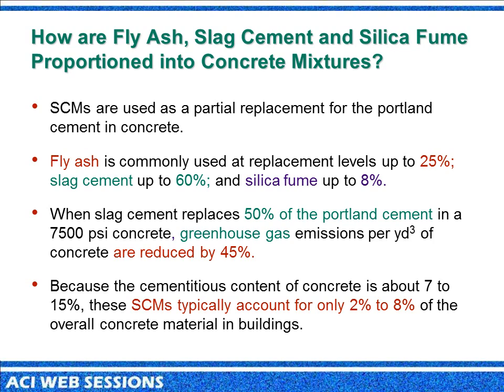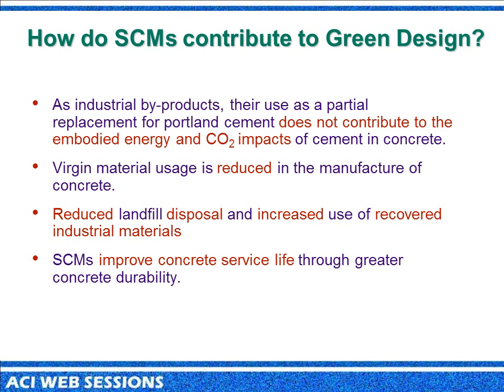With greenhouse gas emissions, if we would replace 50% of the Portland cement with slag cement in a 7,500 psi concrete mixture, we could see a reduction of upwards of 45% of the greenhouse gases that would be produced in that concrete mixture. And this is where we really start to see the advantage of using our supplemental cementitious materials. As industrial byproducts, the use of slag cement also does not contribute to the embodied energy up front, and helps also in lowering the CO2.